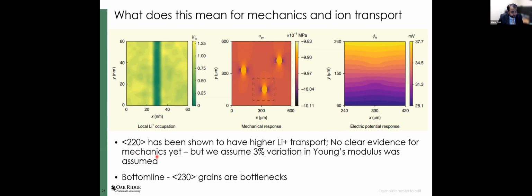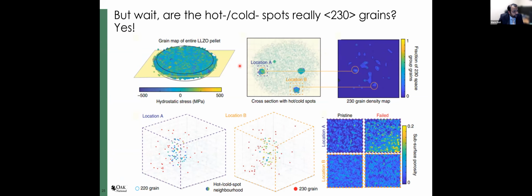What we haven't shown yet is whether these two are co-located. So that's a question that we wanted to answer, whether the regions of high stress and low stress that we identify are also the regions where these secondary polymorphs are present in the solid electrolytes. And so this is what we observed, right? If you take a cross section of the hot spot and cold spot, where these clusters of grains are essentially grains identified within the vicinity of a hotspot, these correlate extremely well to the regions where we see a high number of 230 space group grains.